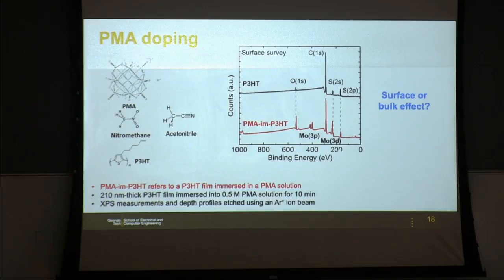And so what X-ray photoemission spectroscopy gives you is signals of different orbitals of different elements, and so you can see here that in a film that's been dipped into a PMA solution for just 10 minutes here, and at 0.5 molar, you can see these peaks appearing, which are signatures of the molybdenum, while, of course, in a neat film of poly-3-hexyl-thiophene, you don't see these signatures because there is no molybdenum in there.